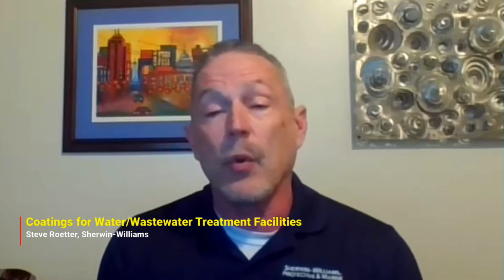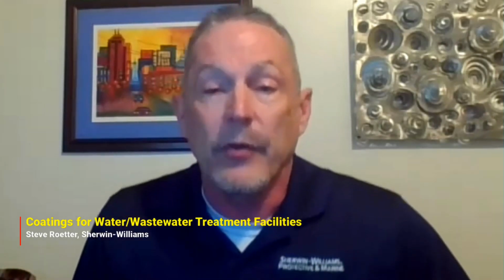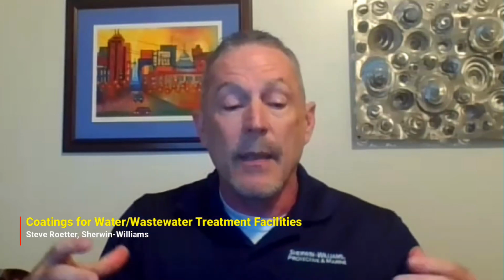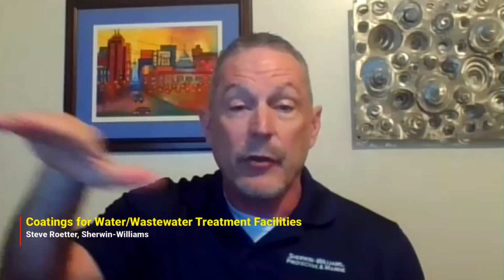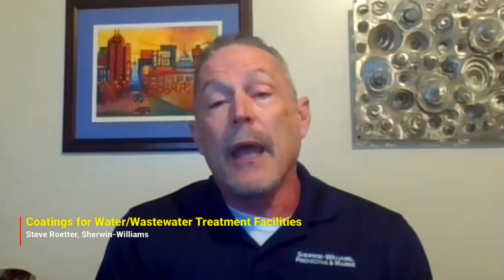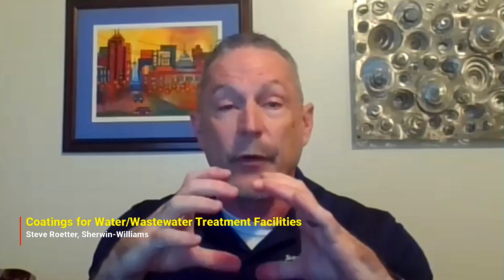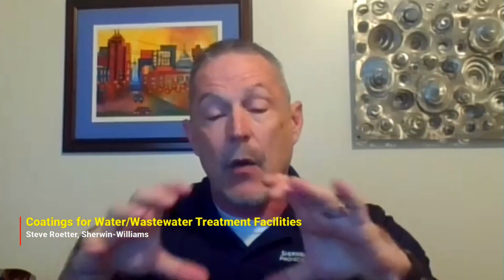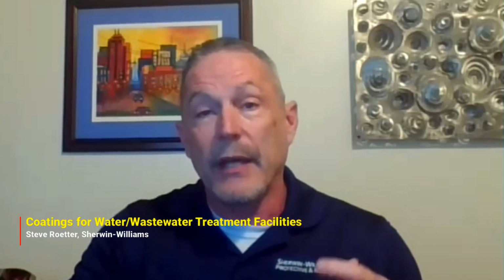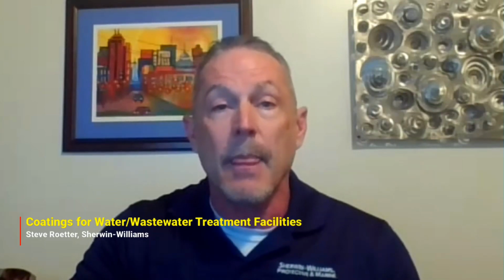The second is the trend towards regional sewer districts. So this trend has significantly expanded the footprints of these sewer systems, which has required longer travel times in the pipes, longer detention time, and this sewerage becomes more septic the longer it sits in these piping systems. It's also necessitated more force mains because they have to travel longer distances. You can't get gravity feed over those long distances. And the force mains now have caused these pipes to run full as opposed to half. So now you get this slime layer around the entire diameter of the pipe. So more bacteria now are present to act on the sewerage. And so these two factors have really caused a significant increase in the hydrogen sulfide production in wastewater.